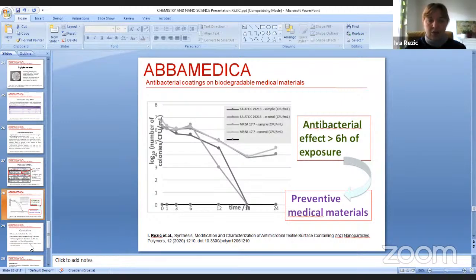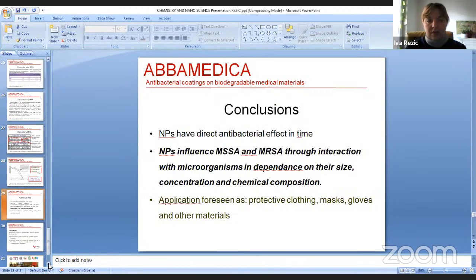So what we can conclude from this short presentation is that nanoparticles of metals and metal oxides really have a direct antibacterial effect with time, and for this reason are excellent coatings for medical materials. What we saw also is that metal nanoparticles influence MSSA and MRSA through interaction with microorganisms, and this interaction was dependent on the size of the nanoparticle, on its concentration, and also on its chemical composition.